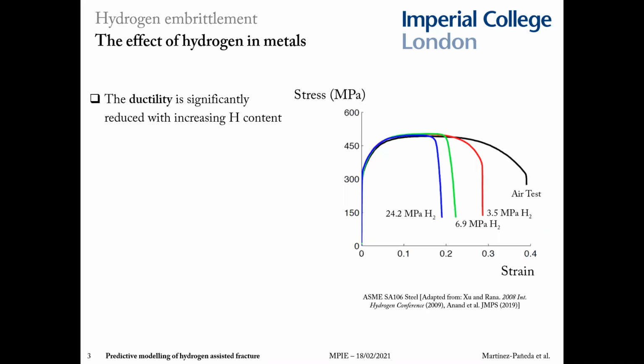One of these effects of hydrogen in metallic materials is how the ductility reduces significantly with increasing the amount of hydrogen. You can see here uniaxial stress strain curves. And if we introduce hydrogen into our specimens, for example, by exposing them to hydrogen gas, then we see a very strong reduction in the failure strain.